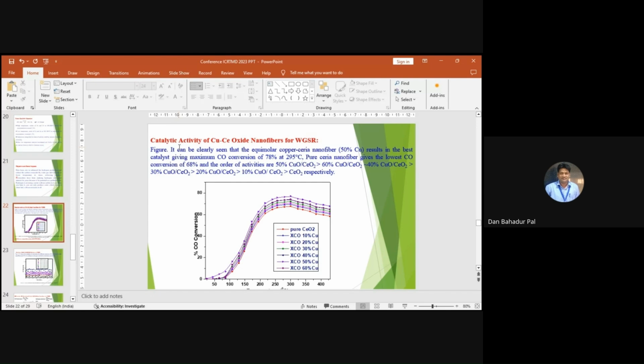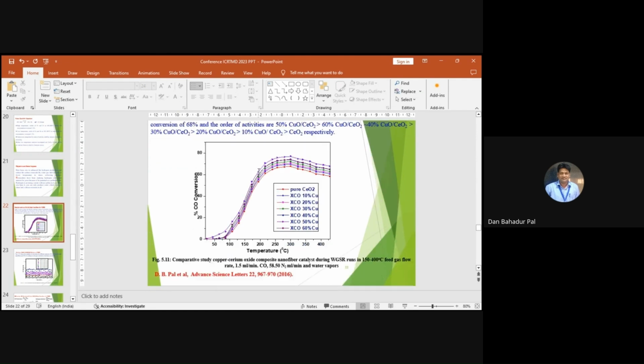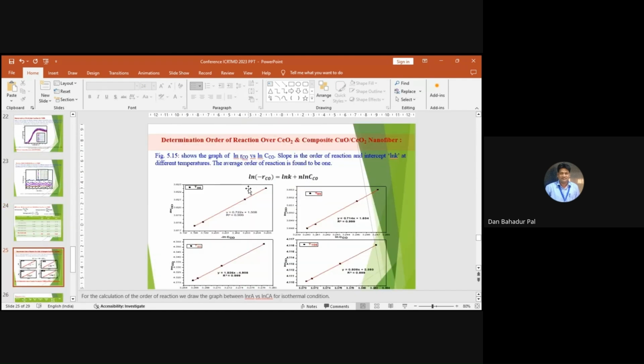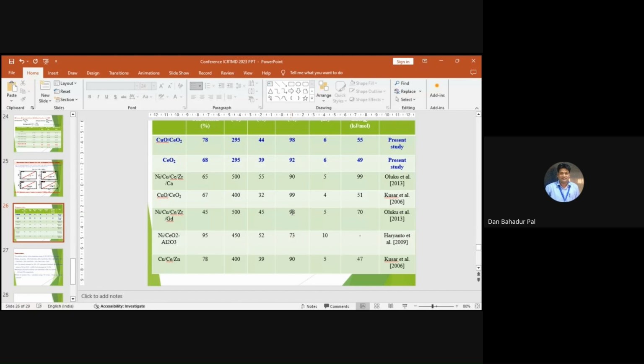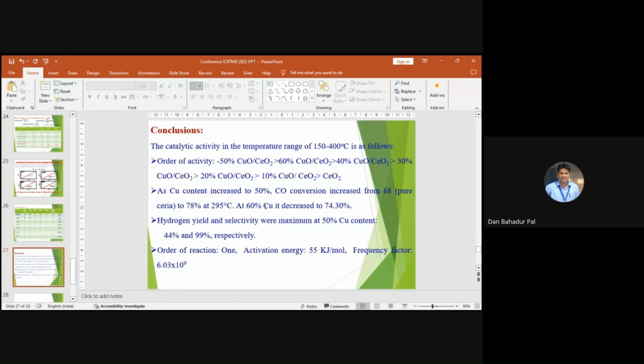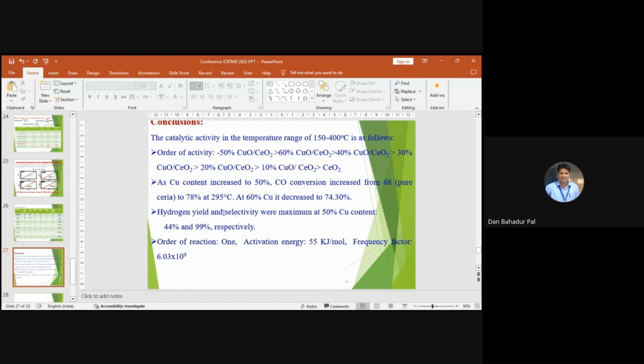This is the catalytic activity study, and here we also determine the kinetic study. This is the comparative study of present work and past work. This is the conclusion. The catalytic activity was tested in the temperature range of 150 to 400. Following the order of activity, the 50% composition gave the best result, and pure ceria gave the worst result as per the study. So this is regarding the work, and thank you.